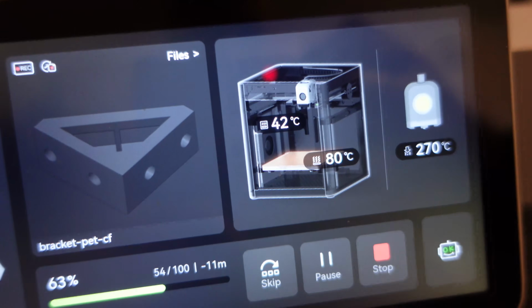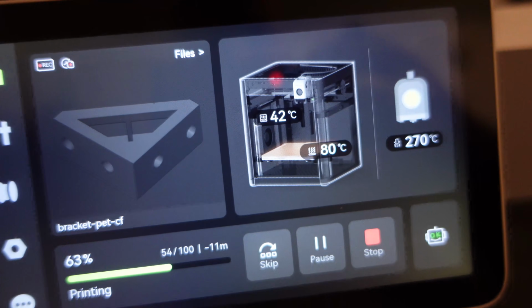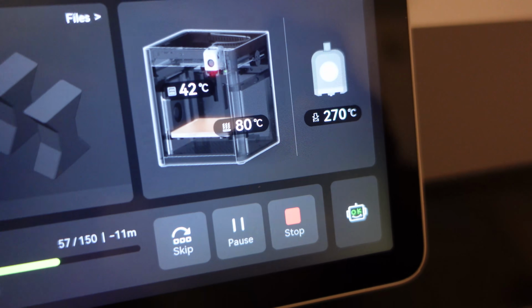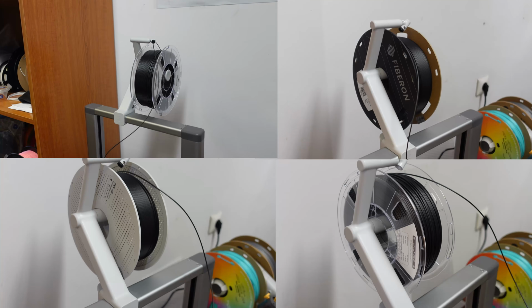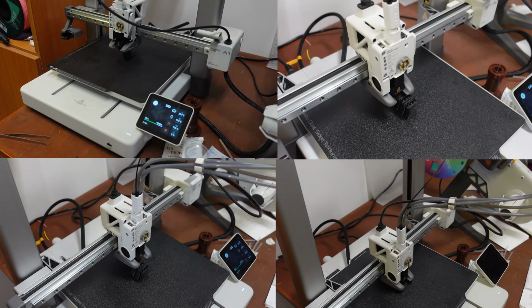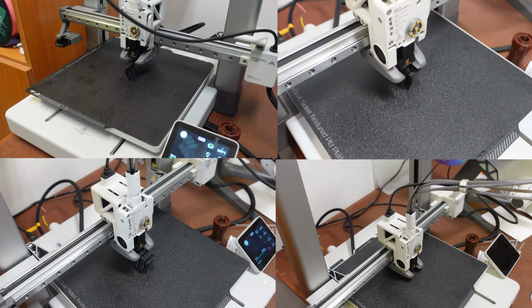This is the bracket, printed at 270 degrees Celsius. But also I want to check the layer adhesion, how much weaker it will be if I print it at a lower temperature. Layer adhesion test objects are reprinted on BambuLab A1, which is an open printer.